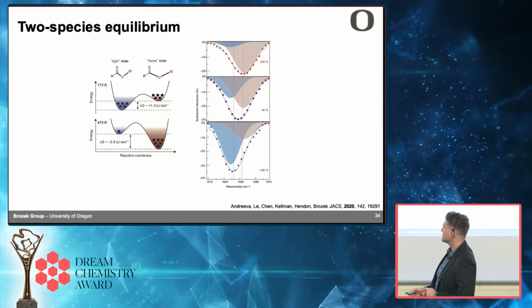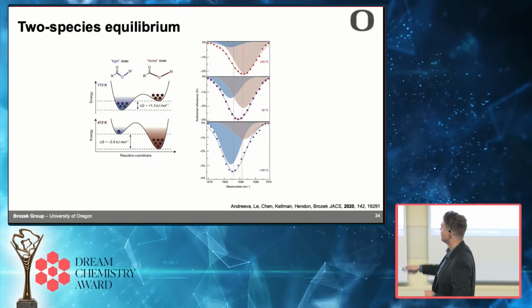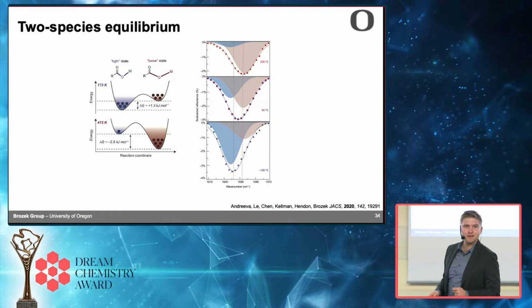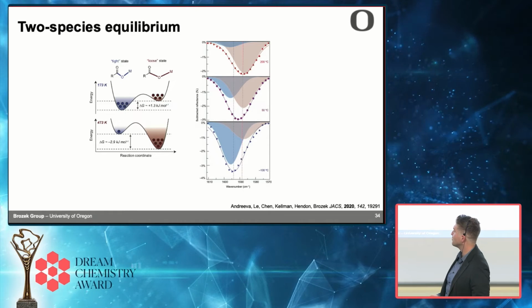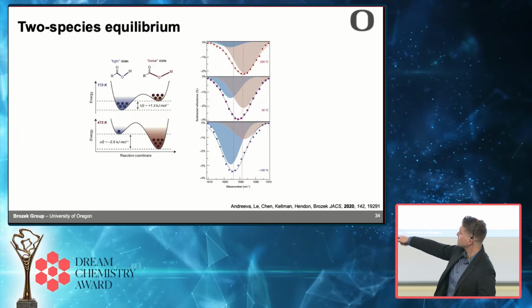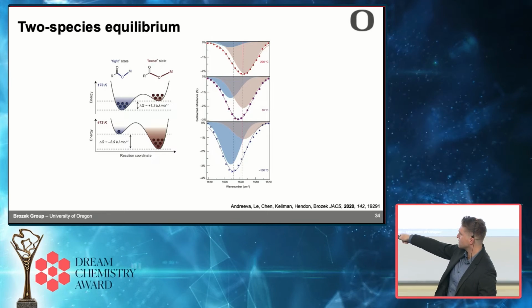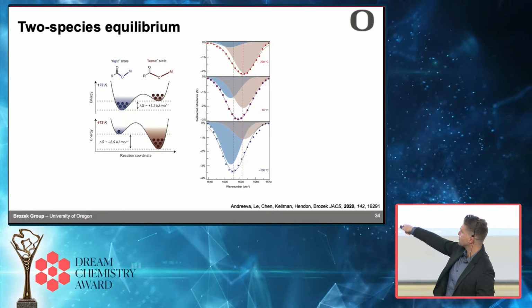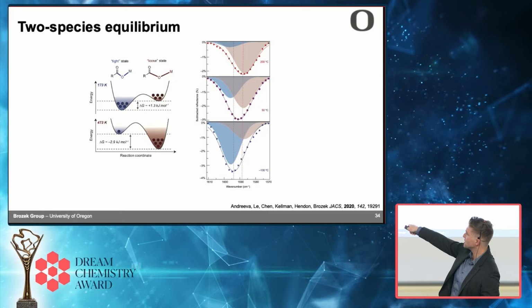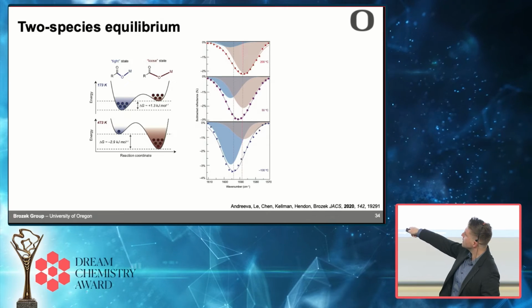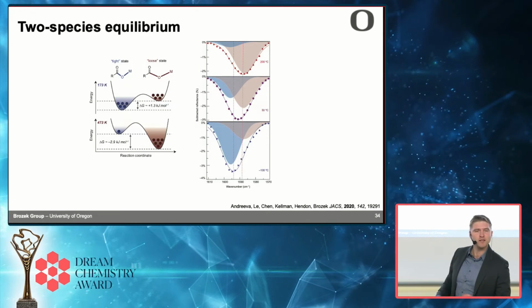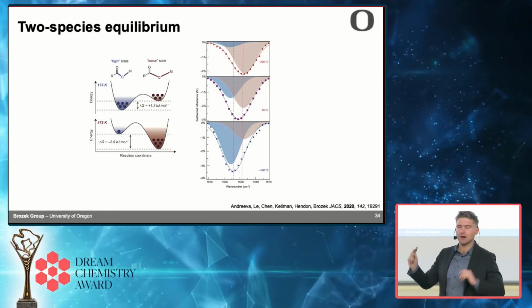So here's the asymmetric carboxylate stretch again. We can fit it to a two species model, global fitting model. And we see that at low temperature, you prefer the high frequency species. At high temperature, you prefer the low frequency species. And at intermediate temperatures, you see both of them. And that's why the peak is broadest, because they're both there.